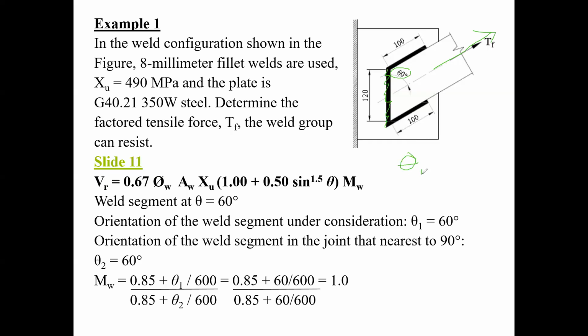Now, which weld segment is closest to 90 degrees? Also the 60. So in other words, this theta 2 is 60, and this will always be theta 2 for this problem. But the theta 1 changes depending on the weld segment I'm considering. I did this for academic reasons, to show you that when the weld segment under consideration is the same as the weld segment that is closest to 90 degrees, then the value of Mw ends up being 1.0.